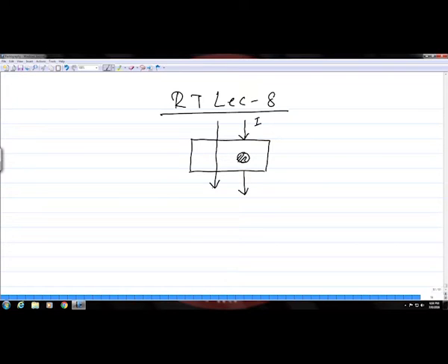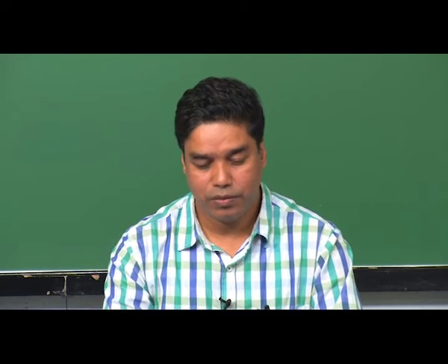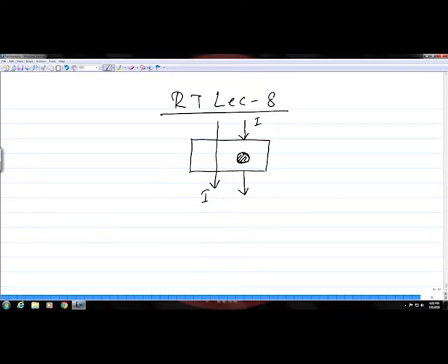in order to identify the defects. When it is exposed to X-rays, the X-rays will go through the material and finally they will encounter the defect. So, they will also have to pass through this particular defect. On the other hand, where there is no defect, they will simply go through the material. So, you can expect two different intensities coming out, one from the parent material itself, let us say that is I1, and the other from the defect, which is I2.